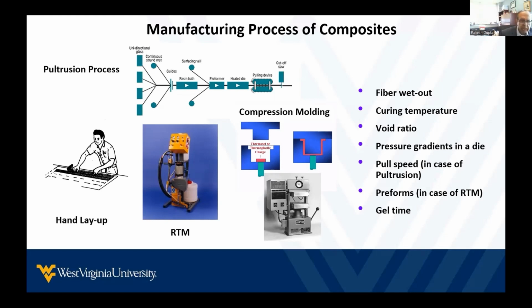A continuous operation is pultrusion. Here one starts with unidirectional glass fibers and continuous strand mat. It goes into a resin bath. You pick up the resin. The material then goes into a preformer where excess resin is squeezed out, and then the resin infused reinforcement goes into a heated die. Within the die, curing takes place, and what emerges from the die is a solid part. It's pulled by a device, and then what emerges from the device is cut to the appropriate size.